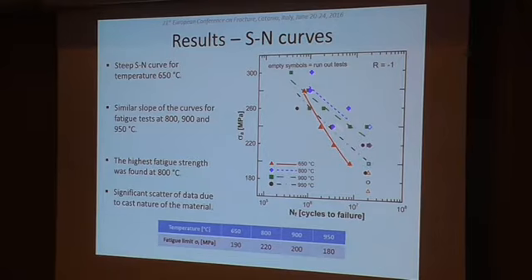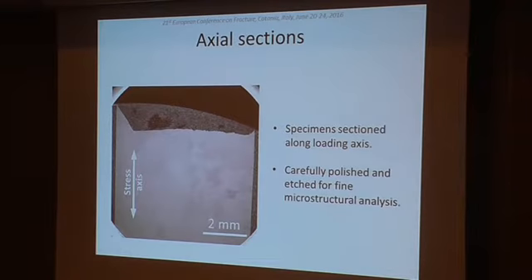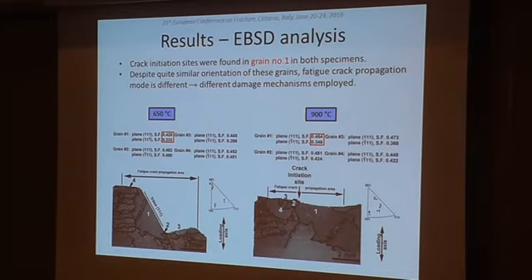After these measurements of fatigue tests and plotting of these curves, we focused on explanation of this different slope. We prepared axial sections along the loading axis by polishing and etching to prepare samples for scanning electron microscopy observations, and one of the first observations or analyses was EBSD analysis.